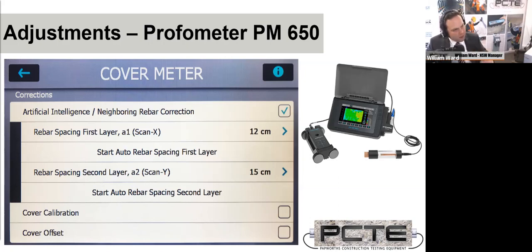The other thing is, we talked about with rebar how the moisture content affects your cover depth measurement or your depth measurements on a ground penetrating radar. Cover meters are not affected by moisture content. So they can even be used underwater or on freshly cast concrete.